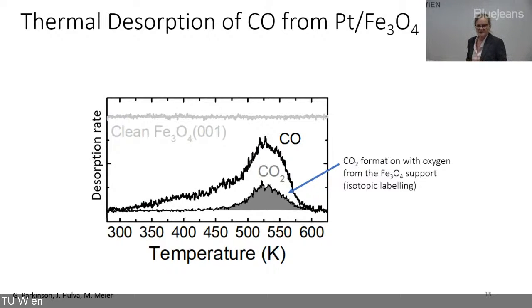What you can see on this plot, on the x-axis, is the temperature of the sample, from room temperature up to 600 Kelvin as it's heated up. On the left-hand side, you can see how much carbon monoxide is desorbing from the sample - that's called thermal desorption. The gray curve on top is from the clean iron oxide surface, where CO doesn't even stick at room temperature.